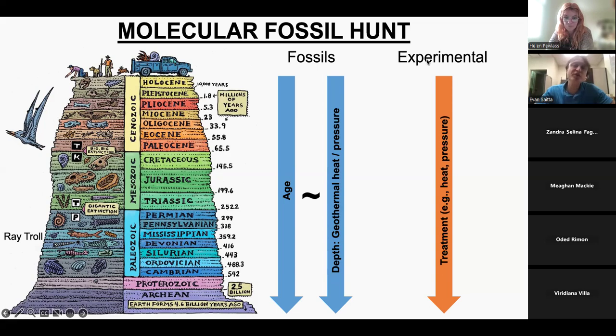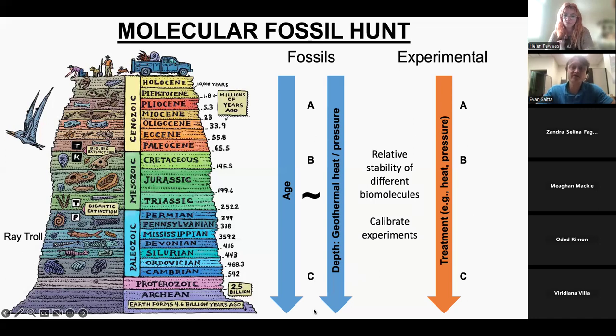And then what you can do is you can mirror this. You can parallel this experimentally by applying treatments such as heat and pressure to various samples to sort of mimic this spectrum, this continuum of degradation. The idea then being that in both your fossil record and your experimental conditions, you get a series of relative stabilities of different biomolecules, A, B, and C in this case. And then, of course, you can use the fossil record to calibrate your experiments, the treatment, how much heat, how much pressure, in order to get a result that matches with your fossil of interest.